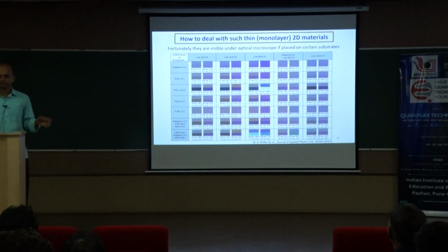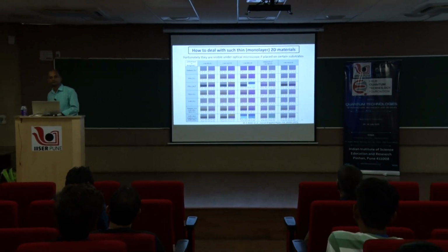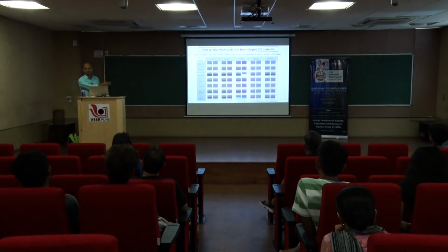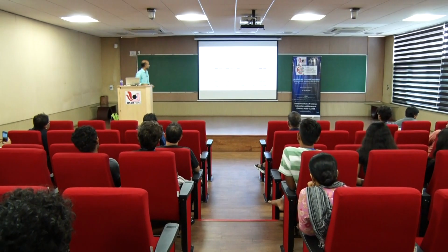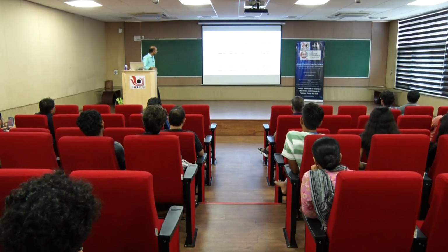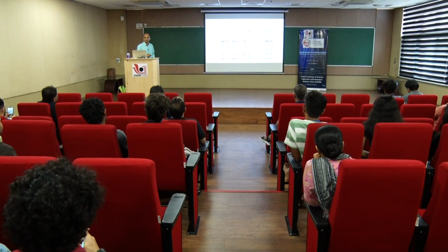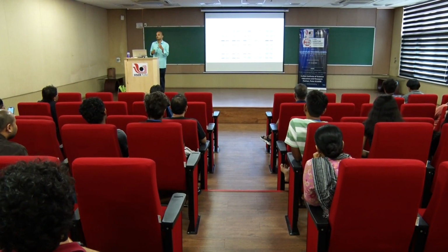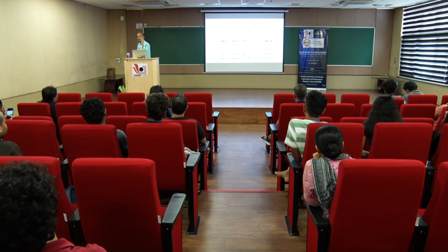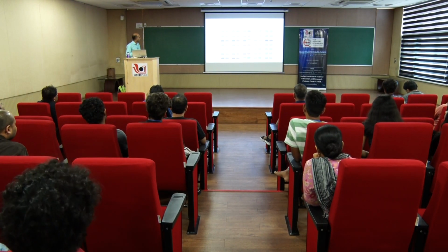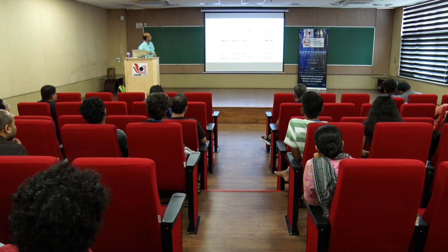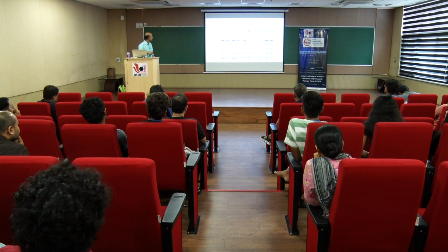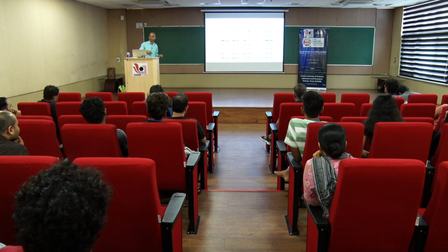Okay, probably one day you are making 50 devices, and you cannot do 50 times AFM or Raman to figure out whether I have a monolayer or not. So, this is a great discovery, where people figured out that on a certain substrate you can see a monolayer. And in this paper they have shown for various types of substrate what is the thickness of that SiO2 or the insulating material required.